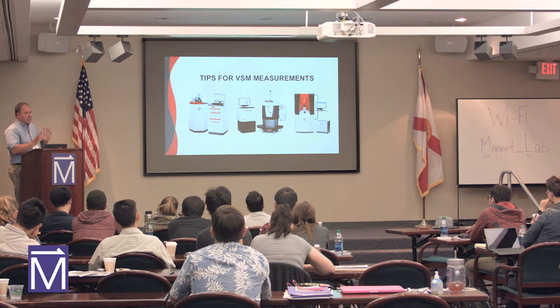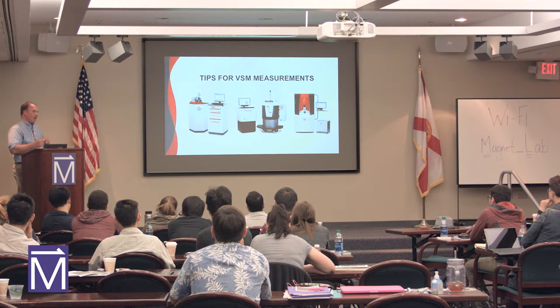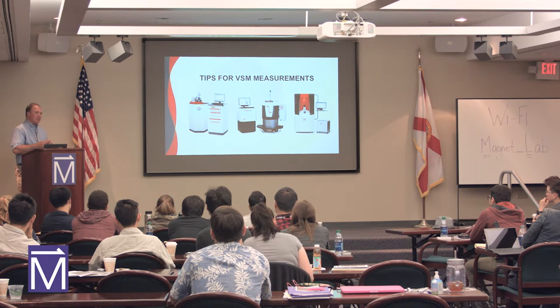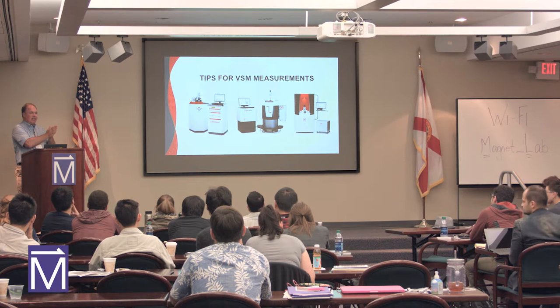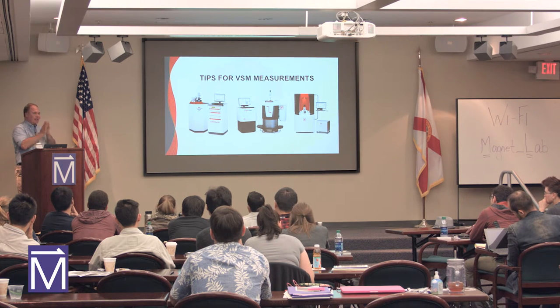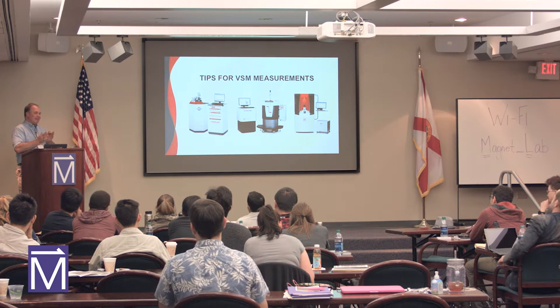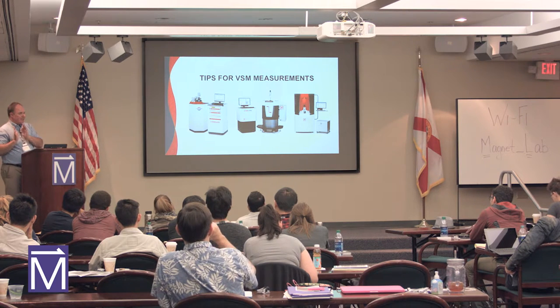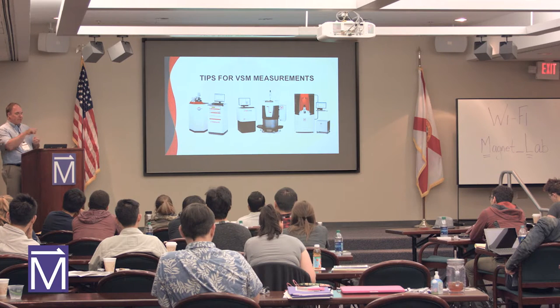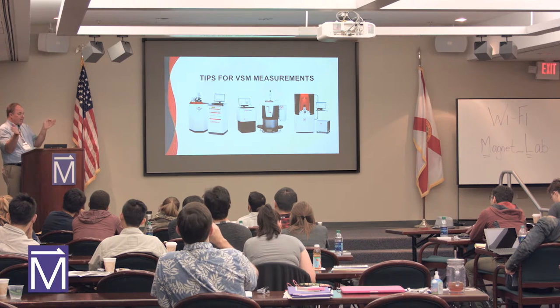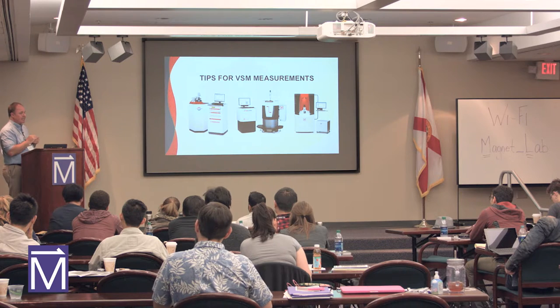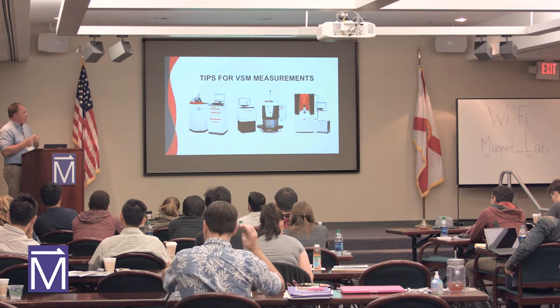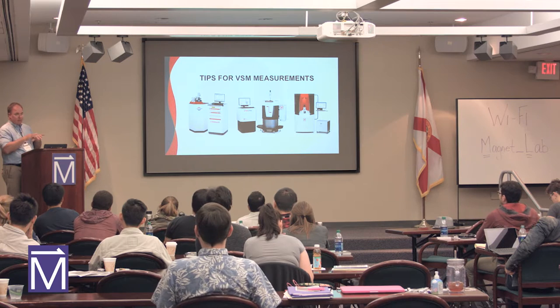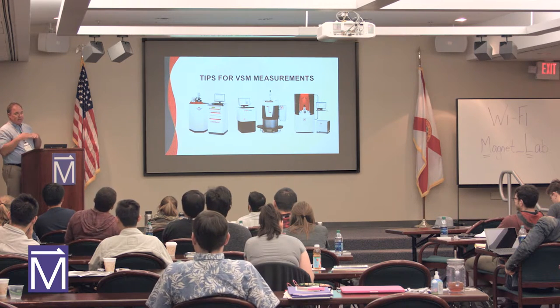So our engineers came up with an idea, hey, if we use the VSM head with the SQUID, we can come up with a SQUID VSM. So we had this SVSM, the SQUID VSM system that we came out with. We had the DC SQUID, MPMS XL. We came out with a SQUID VSM, and we've moved it back to a DC SQUID system. We branched off the SQUID measurement technique into this SQUID VSM measurement. There's a couple of these systems here in the magnet lab, but they still do a DC SQUID measurement.